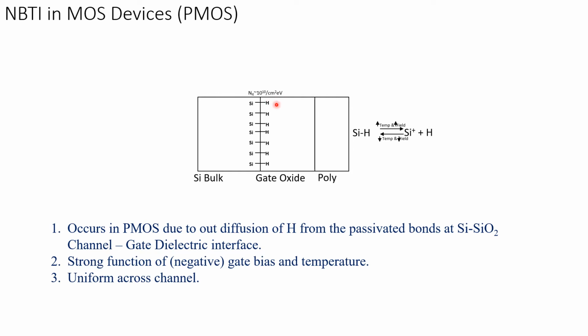And this was the case in the earlier silicon technologies from the 70s, wherein people were not able to get this gate interface between the silicon channel and the gate oxide passivated, and that's why the devices suffered huge degradation in terms of their threshold voltage shifts. Basically, let's say at time equal to 0 you have a certain threshold voltage, at time equal to some t dash, your threshold voltage would have shifted in such a way that you no longer have the device that you actually